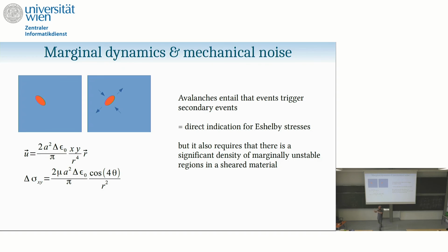So the observation of avalanches, in fact, was the direct proof that the Eshelby mechanism is at work. The fact that we see avalanches demonstrates that events talk to each other, that different regions of the system interact, and the only way they can interact is through stress, right? Because that's what you propagate. So you have this change of mechanical balance.